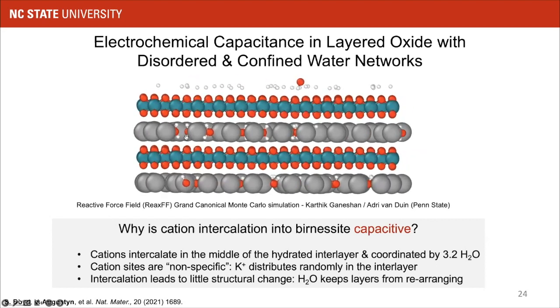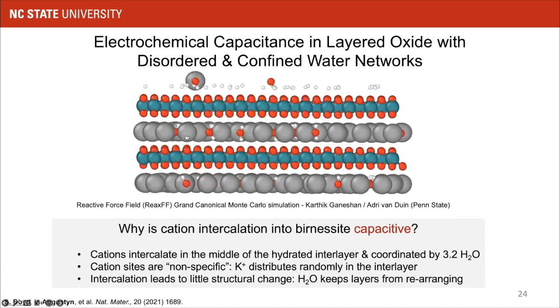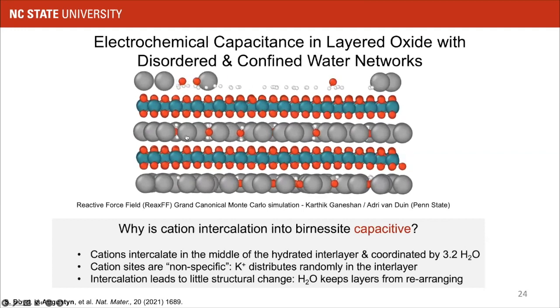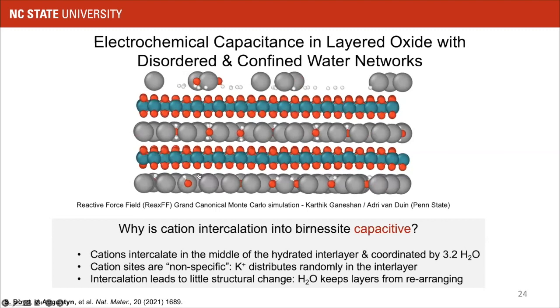The cations like potassium, these gray spheres, are intercalating in the middle of the hydrous interlayer, and they're coordinated by other water molecules within the interlayer. Their locations are nonspecific, so they distribute randomly in the interlayer, and that's why you would see a lack of potential dependence. And very importantly, very little structural change takes place because you have this counter movement of water molecules, or water molecules that again remain as kind of pillaring molecules within the interlayer.